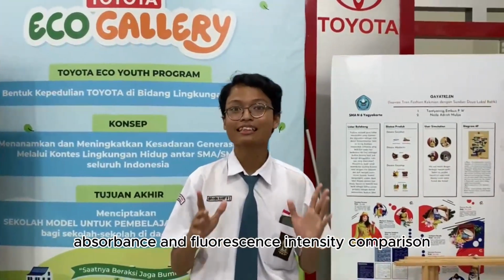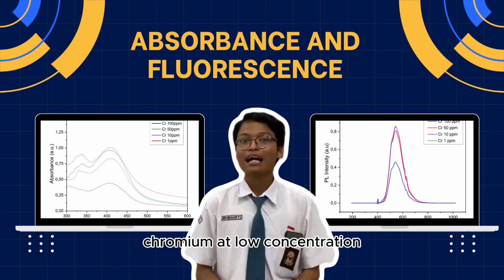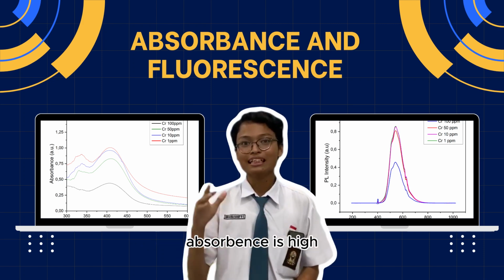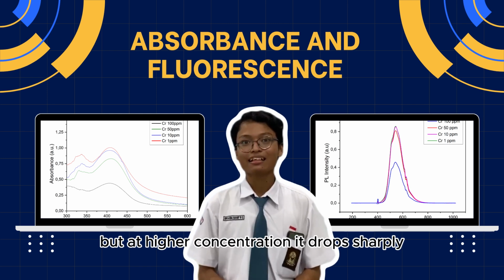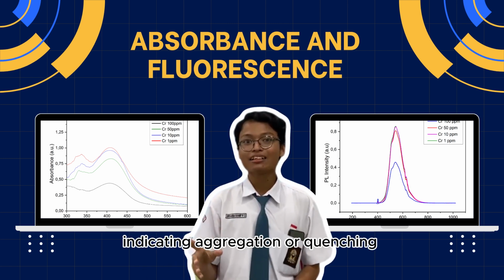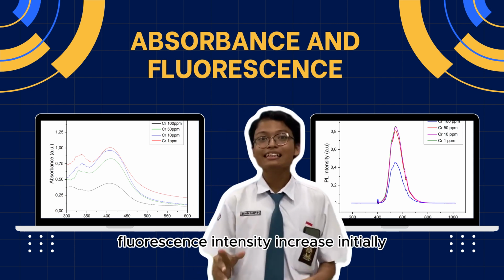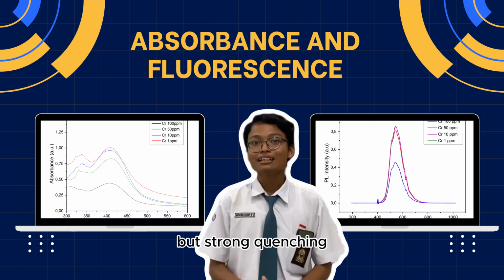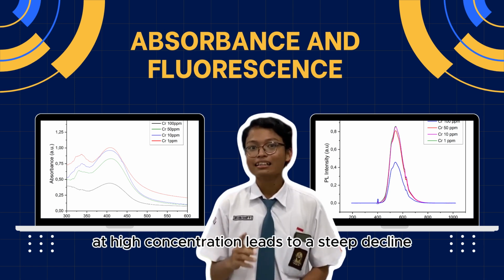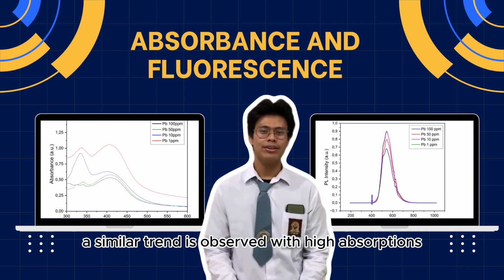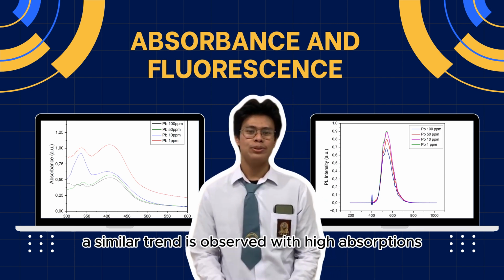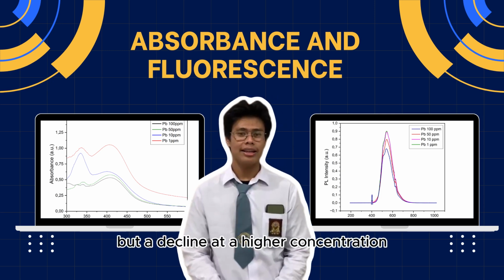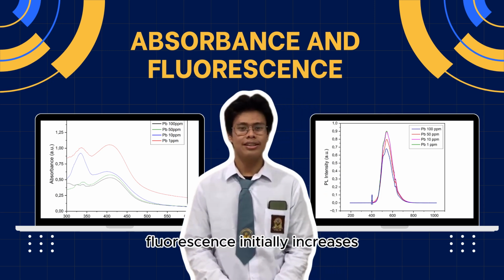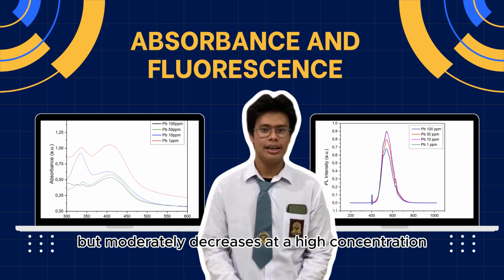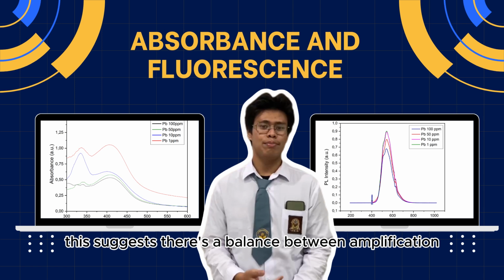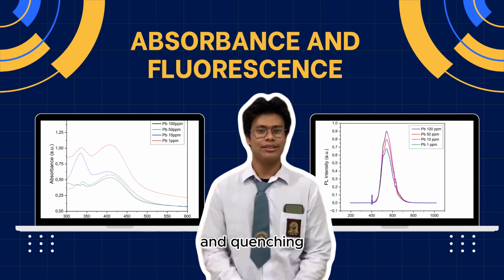Absorbance and fluorescence intensity comparison. Chromium: at low concentration, absorbance is high, but at higher concentration, it drops sharply, indicating aggregation or quenching. Fluorescence intensity increased initially, but strong quenching at high concentration leads to a steep decline. For lead, a similar trend is observed with high absorption at a low concentration, but a decline at a higher concentration. Fluorescence initially increases, but moderately decreases at a high concentration. This suggests there's a balance between amplification and quenching.